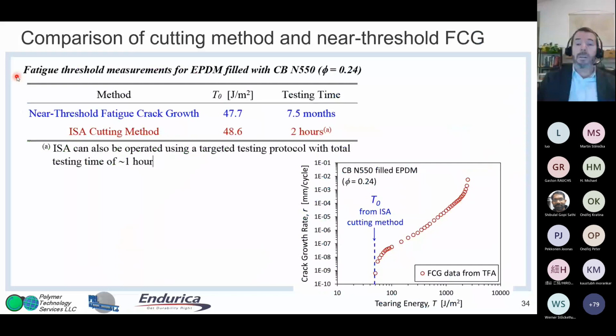So now we can compare this cutting method to the near threshold fatigue crack growth. Again, that very long experiment of 7.5 months that got a value of 47.7. And what you see is, using this ISA cutting method, you get pretty close, nearly identical in only 2 hours. And so you can see the value of this technique and why it's really going to change the way people are able to quantify this fatigue threshold.